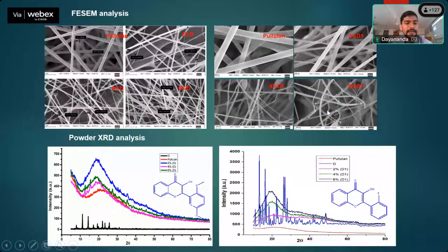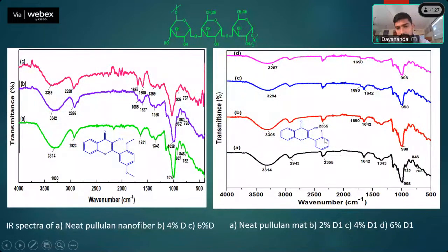To understand the interaction between pullulan and dopant, FTIR was used. From FTIR, one could see that for the fluorine containing dopant, it interacts with the pullulan backbone through hydrogen linkage. That is why there was a shifting of the OH band - the hydroxy group whatever is there in the molecule was shifted towards lower wave number.